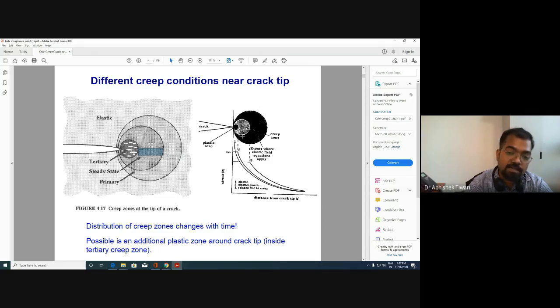It's just that the total deformation, let's say the total strain amount is epsilon T. So that total strain will have some component which is time dependent and some component which is not time dependent. You can also break the total strain between elastic part and non-elastic part. And the non-elastic part will have again two components. One will be time dependent, another will be not time dependent. So the time dependent part will be creep, non-time dependent part will be plastic strain.